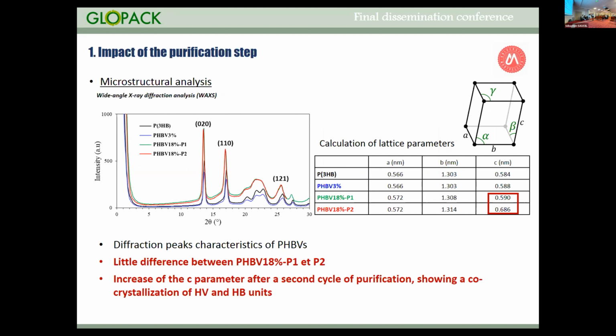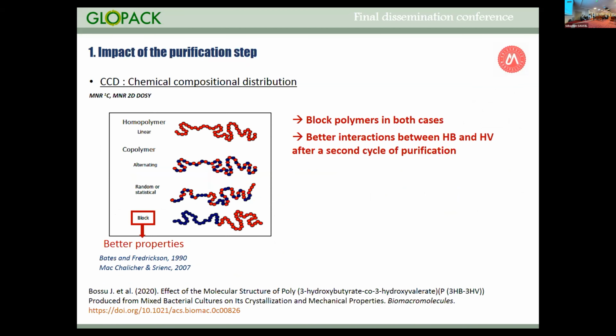And you see that, okay, globally it's not very impacted if you only have a look on the patterns between the two purification levels. But if you measure the lattice parameters, you can see that you have a significant increase of one dimension of the lattice. And this was an indication of a better co-crystallization of HV and HB units. And another key information was deduced from advanced NMR techniques.